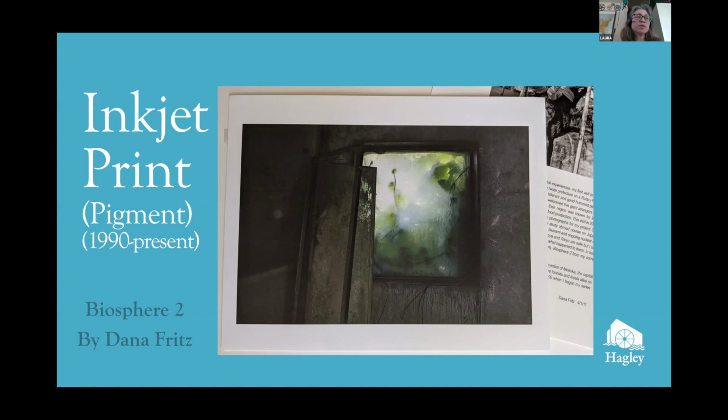Even though they are more recently made, digital photos printed with modern technologies are, in general, more susceptible to damage than prints from the 20th century. Inkjet printers may use dye-based or pigment inks. Dye-based inkjet prints in particular are likely to fade and are especially sensitive to the pollutant ozone. The dyes are highly susceptible to bleeding from moisture and humidity and fading from pollutants.